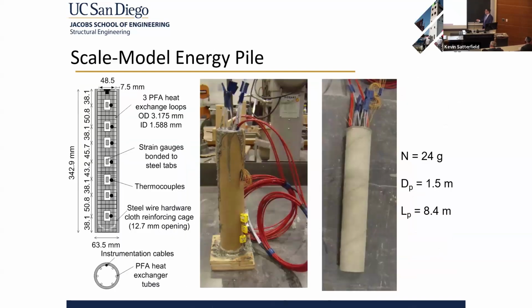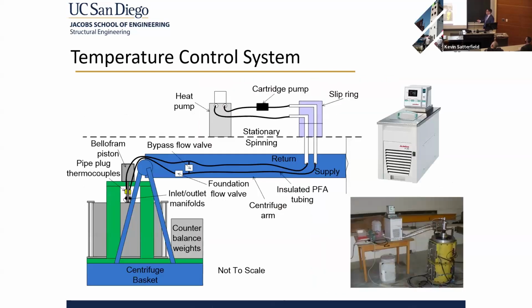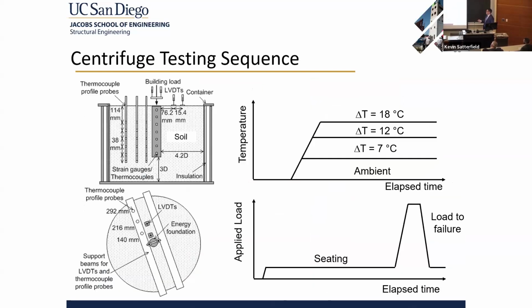So this is our scale model energy pile that we looked at for the unsaturated soil tests. This is reinforced concrete with chicken wire and different strain gauges, which is pretty tricky to build. And we had a heating unit that went through some slip ring stacks down through our energy pile in the centrifuge, spinning around at 24 Gs. And then we made measurements.